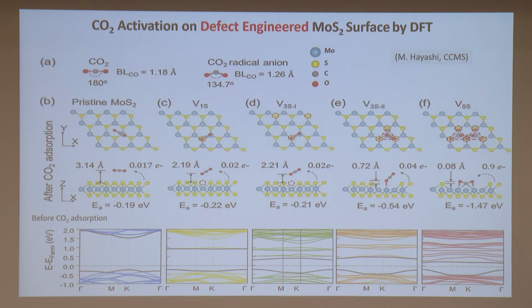Now, the untreated surface, presumably a perfect surface, was calculated by my colleague who is a theoretician. What he told us is that CO2 can come as close as 3 Angstrom. 3 Angstrom is not considered chemical bonding at all. It's mostly just physisorption, if they do stay, okay? And charge transfer is almost negligible. Now, with a single vacancy, the CO2 can come a little bit closer, but still 2 Angstrom away, and also very minimal charge transfer, okay? And scattered 3 vacancies, also similar, they don't do anything.